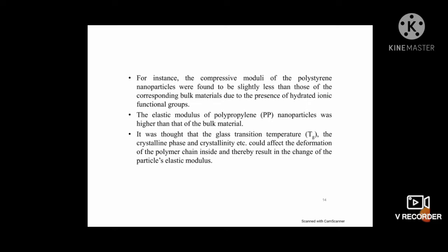So here we will compare an example of a nanoparticle with its bulk particle. For example, we study the property of compressive moduli of polystyrene nanoparticles. We found that it is slightly less than the corresponding bulk material, and the reason is the presence of hydrated ionic functional groups.